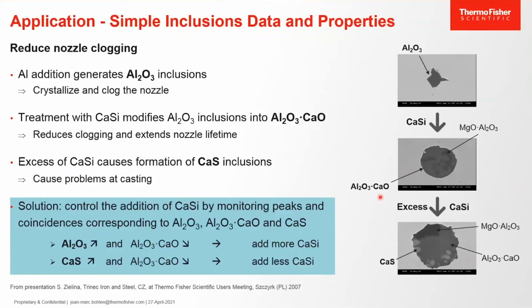So the solution to control that and get only calcium aluminate inclusions and no aluminum oxide or no calcium sulfide inclusions is to control the addition of the calcium compounds by monitoring the peaks and coincidence corresponding to aluminum oxide, calcium aluminate, and calcium sulfide. So the idea is that when aluminum oxide inclusions increase and calcium aluminate inclusions decrease, you have to add more calcium compounds, and when calcium sulfide increases and calcium aluminate decreases, less calcium compounds have to be added in order to have a smooth process.